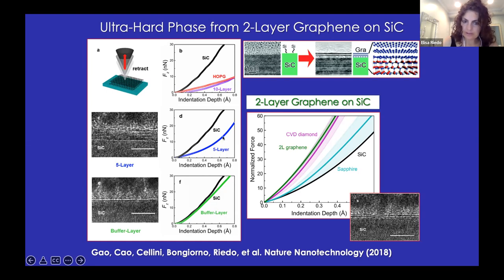For 5-layer graphene on silicon carbide, the stiffness is a little bit higher because probably we start to feel more the substrate. When we measure the buffer layer, so only this layer here, with nothing on top, we essentially measure the Young modulus of the silicon carbide. Again, nothing unexpected. What really was unexpected was what happened when you have one buffer layer plus one layer. So we call this two-layer graphene. It may be a little bit misleading because, depending on the community you're in, it is really buffer layer plus one layer, but we call it two-layer graphene to indicate that you really have two layers of carbon on top of silicon carbide.